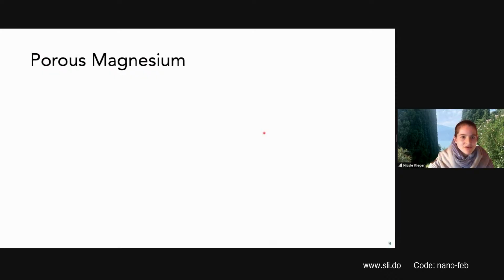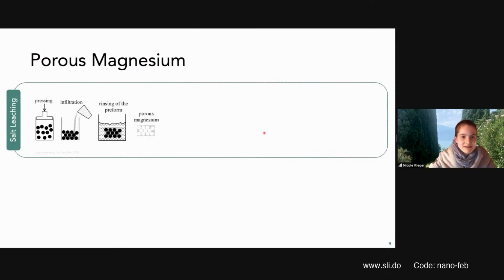Now, there are two methods nowadays that are used to do this. One is a process called salt leaching, which is based on the compression of salt particles in a container. And then these pressed particles are infiltrated with magnesium melt. And as soon as the magnesium melt is cooled down and solidified, we just rinse out the salt in simple tap water. And this makes then our porous magnesium.